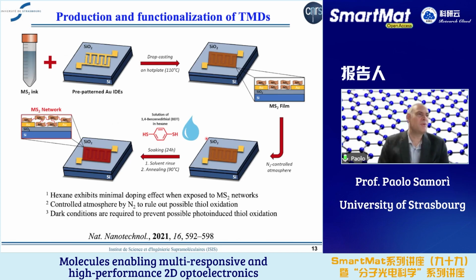And so the way we produce our devices is the following. We start from ink of the MoS2 or other type of disulfide. Then we use some electrodes on silicon that have pre-patterned gold. So these are commercial ones. We spin drop casted the ink on the top of the electrodes. And then at this point, we put the film in a controlled nitrogen atmosphere. And then we place on the top a drop of the benzene dithiol.